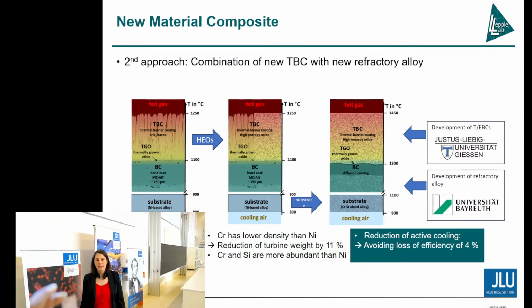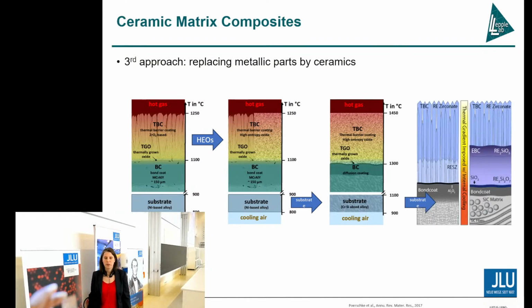To go to even higher temperatures and to also reduce the weight of the turbine, we can then use ceramic matrix composites, which is shown schematically here. So going from the first, we introduced nickel-based superalloy with the TBC, then have a ceramic matrix composite actually as structural element. However, since it's usually made out of carbides, we then also use environmental barrier coating, so protecting the structural material actually from oxidation.